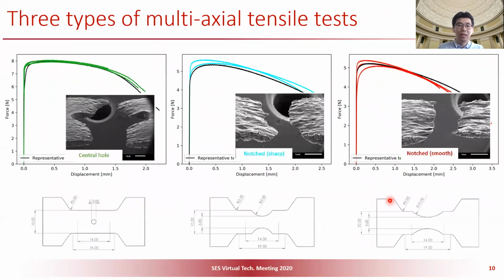Okay. These are the test results of the other 3 types of multi-axial tensile tests. They are uniaxial central hole tension, sharp notch tension, and smooth notch tension. For each of the tests, we performed 3 tests, and the repeatability is quite good. The only difference is here, the smooth notch tension. There are some different behaviors in different curves, but this is still acceptable.